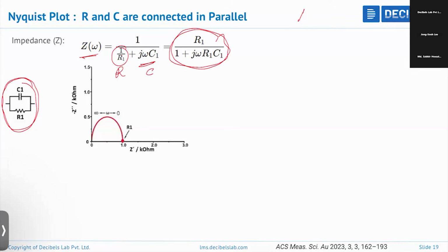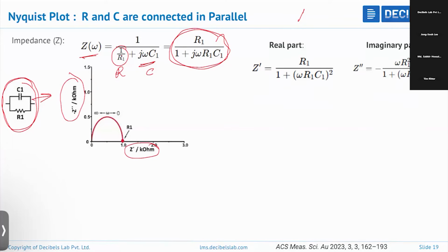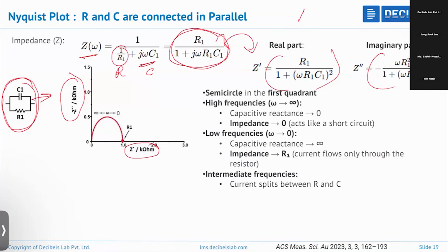The Nyquist plot corresponding to this system, when the capacitor and resistor are in parallel, is a semicircle. This is the imaginary component and this is the real component. The real part, extracted from this equation, is this one, and the imaginary component is this one. You can see the semicircle in the first quadrant. At higher frequencies, omega is high here. In a Nyquist plot, near the origin the frequency is high. As you move away from the origin, the frequency decreases.